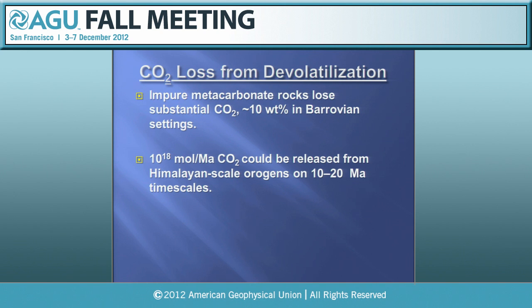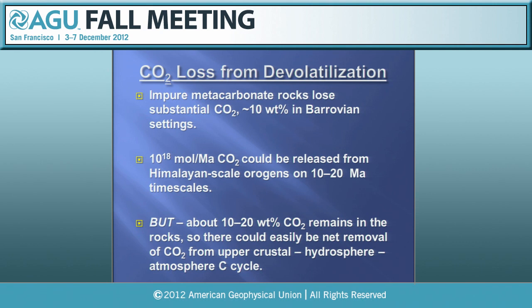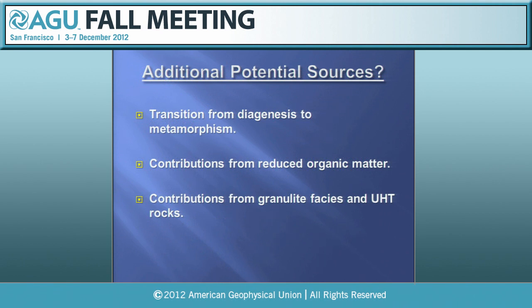But there's one thing I actually haven't told you about, and no doubt you've thought of this already, is that I didn't talk about all the CO2 that remains behind. There's about 10 to 20 weight% on average in the CO2 that stays behind in these rocks, even after they've lost their 10 weight%. So there could easily be some net removal of CO2 from the upper crustal hydrosphere atmosphere carbon cycle, at least on an orogenic time scale, because not all the CO2 is released by prograde devolatilization. That does get released, is well quantified for marls and similar rocks, but there are additional potential sources that we really need to worry about.